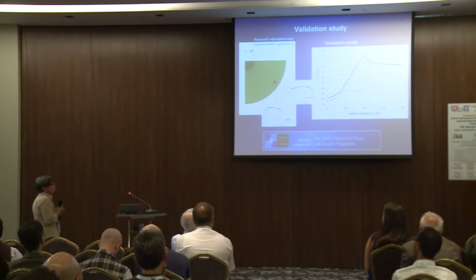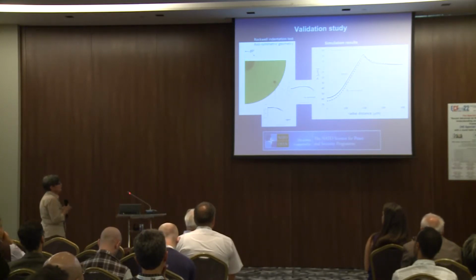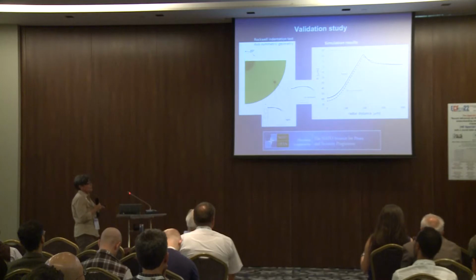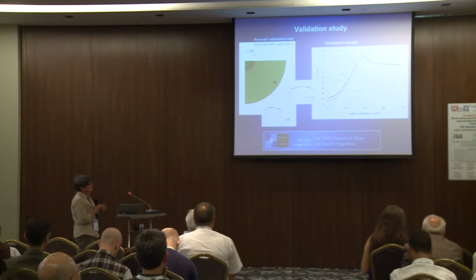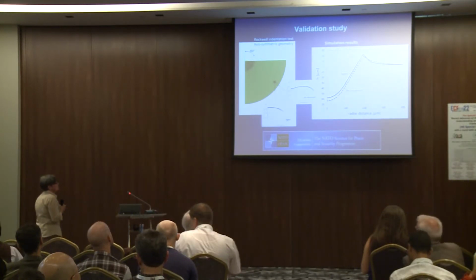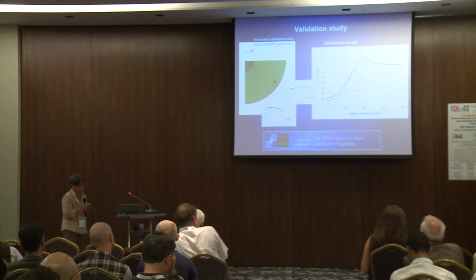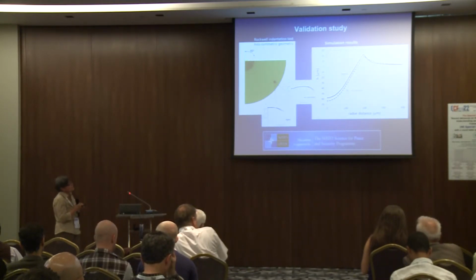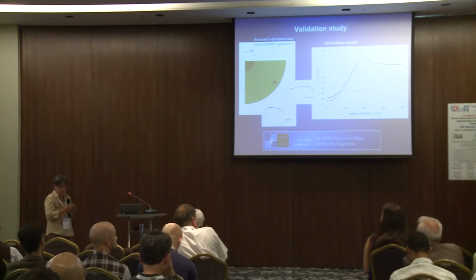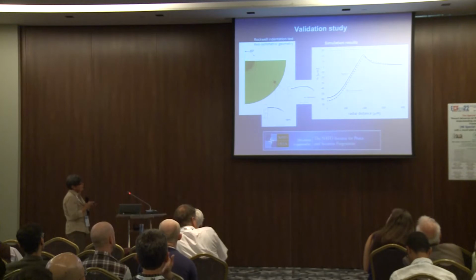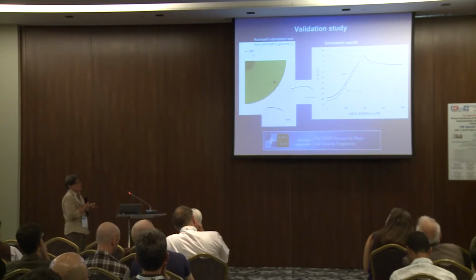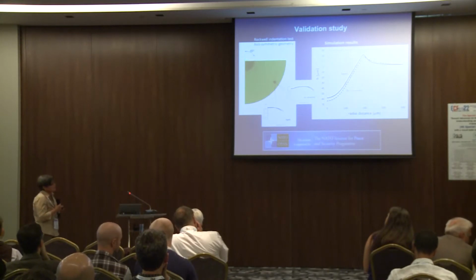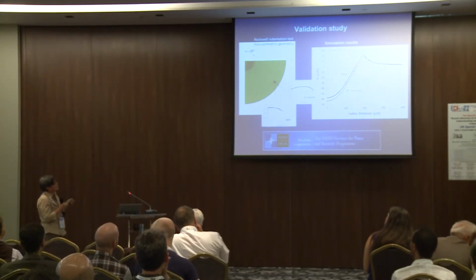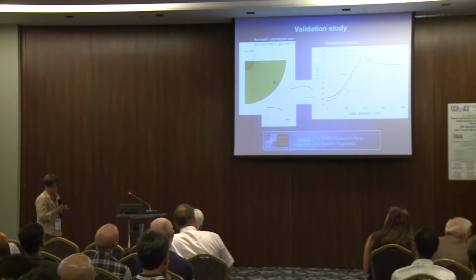The next step of our work will be to check whether, also in this case, we will be able to measure, with the tools that we can use at the present time, also the information which concerns the geometry of the residual imprint. This would be really interesting, both because the prediction that can be obtained from this kind of experimental output becomes more accurate and reliable, and also because this kind of information can be recovered by a simple hardness test, therefore without any need to control the load which is applied to the indenter tip during the test.